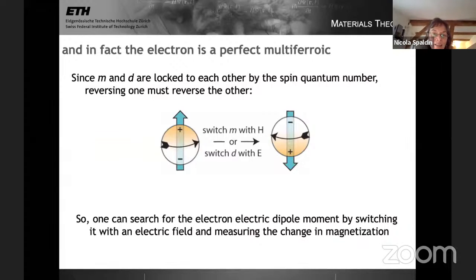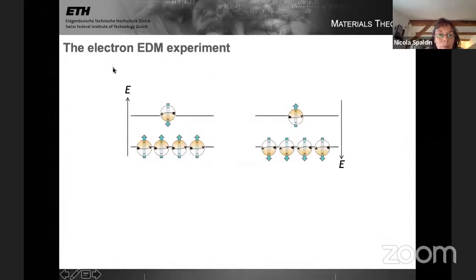And so this property that the electric and magnetic dipole in the electron are locked to each other by the spin quantum number, one can use to search for the electron electric dipole moment. And the way that one does this then is to switch the electric dipole moment with an electric field and measure the change in magnetization. So here's the experiment. We apply an electric field, and then just by the regular Stark effect, the energy for electrons with their electric dipole parallel to the electric field is lower than for electrons with their electric dipole anti-parallel to the field. So we get more, if you like, up dipole electrons than down dipole electrons, just by a Boltzmann distribution. Then we switch the electric field, and now we get more down electric dipole electrons than up electric dipole electrons. And when we do that, we measure the change in the magnetism that happens when we switch the